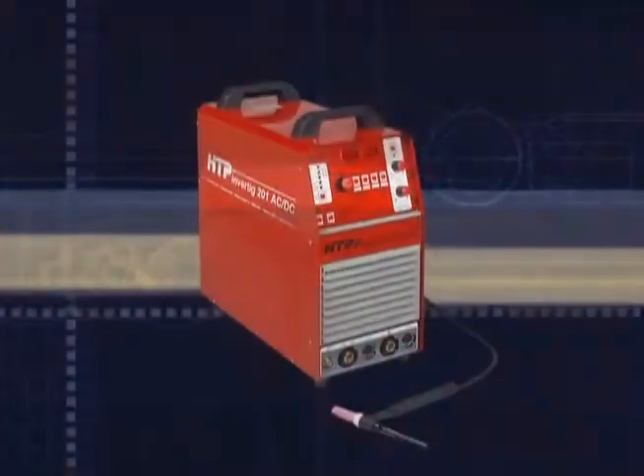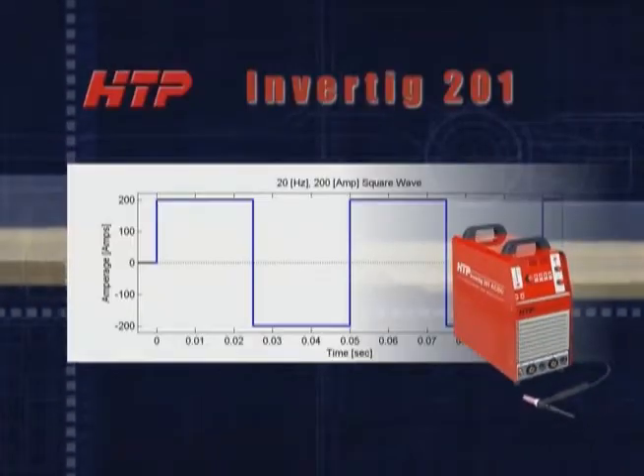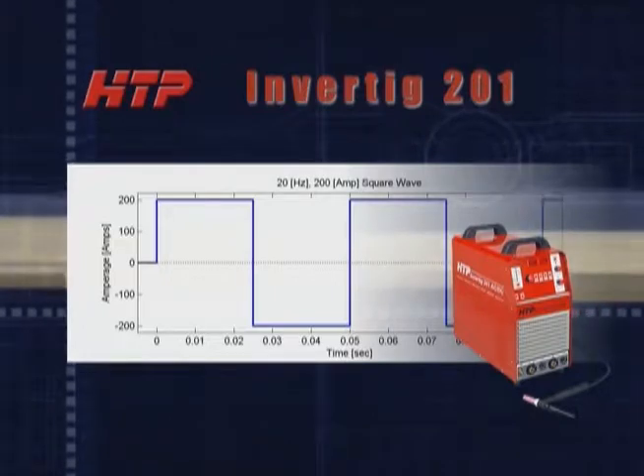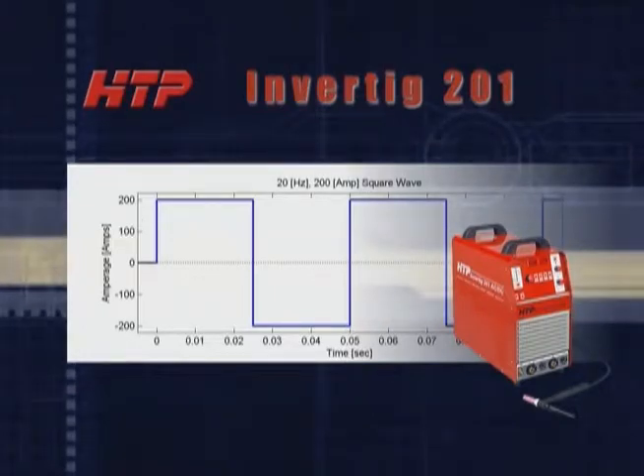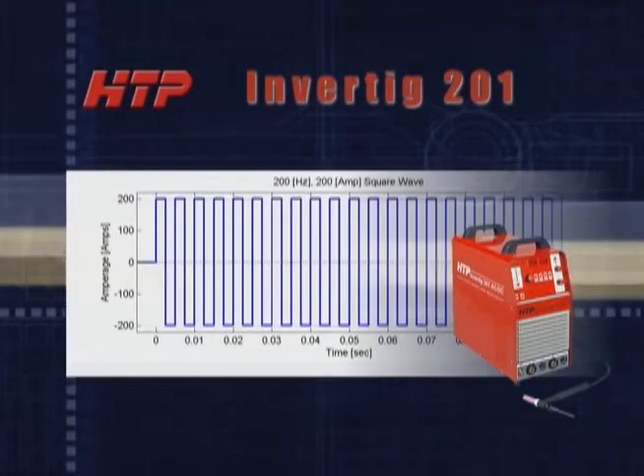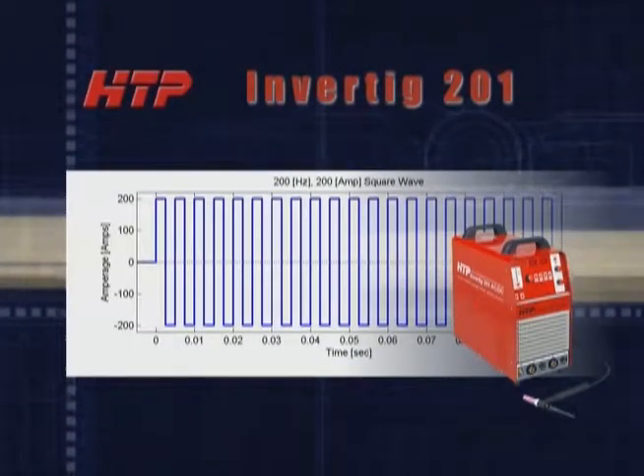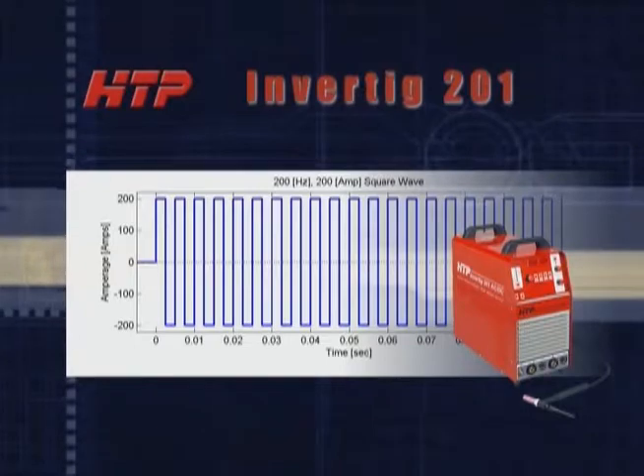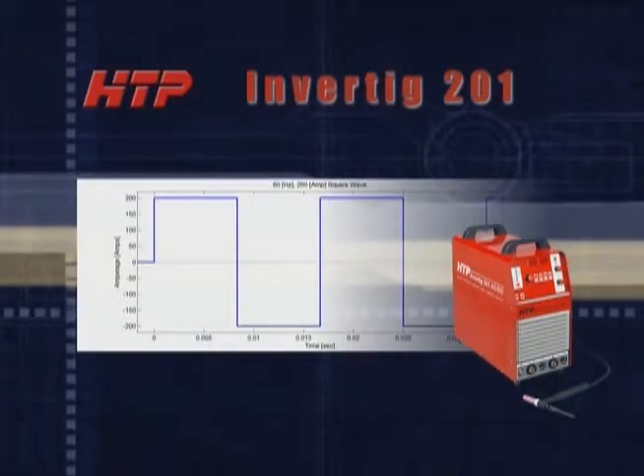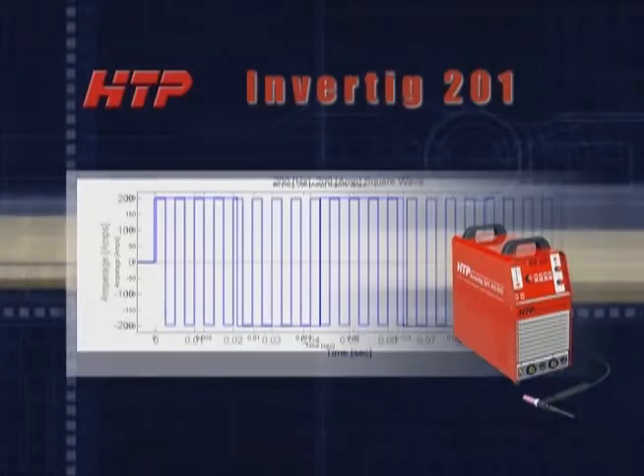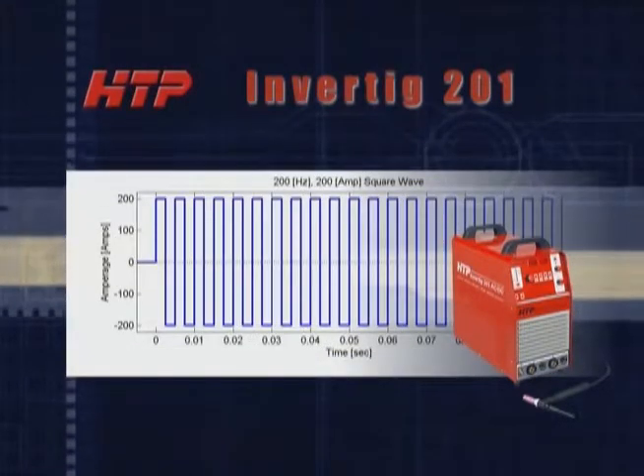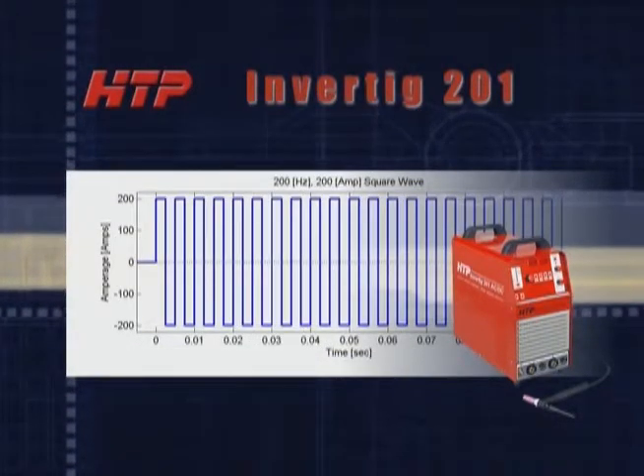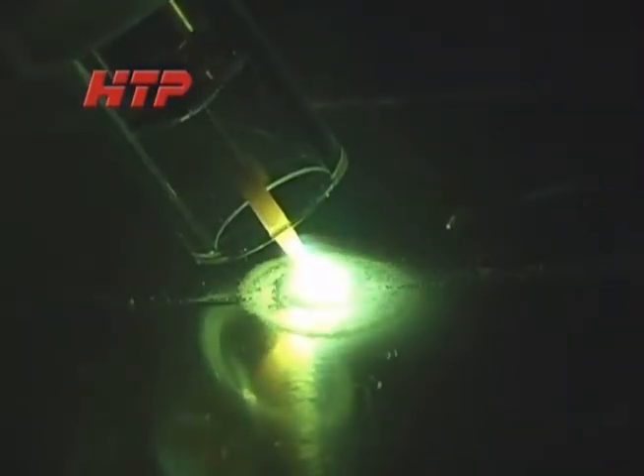The 201 is what you would call an advanced square wave TIG welder. When welding AC, we are able to vary the AC frequency from 20 Hz to 200 Hz. Conventional transformer-based TIG welders have the AC frequency fixed at 60 Hz. Welding with the AC frequency set at 200 Hz allows us to focus the arc to a point, which concentrates the heat and minimizes heat input into the weld.